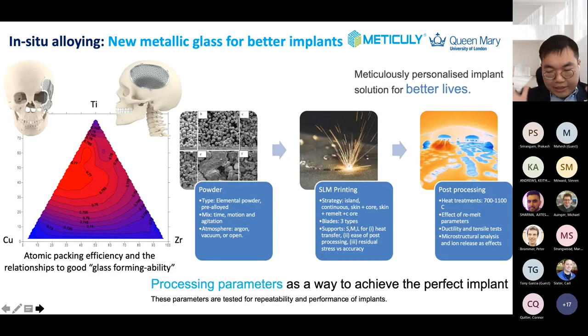So to give you some examples of what we use at the moment, in-situ alloying, or mixing them together under the beam, for a new metal glass composite for a better implant. As you know, traditionally, and what we all use now, is titanium 6-4, medical grade. It's used for biomedical devices. And we have a project under the support of the Royal Academy of Engineering to explore another territory in terms of the process and material system, where we can improve this. So we are looking at a partnership with Thailand, looking at a titanium, copper, zirconium system, where we want to get the processing and the chemistry right to achieve the perfect implant at the end of the day.